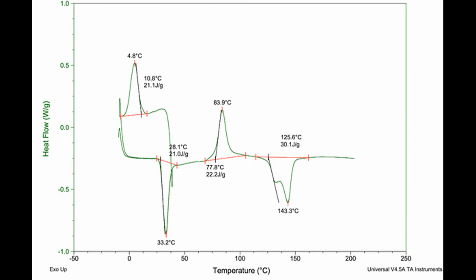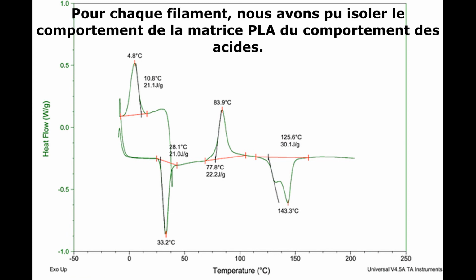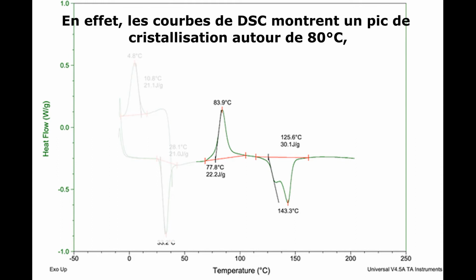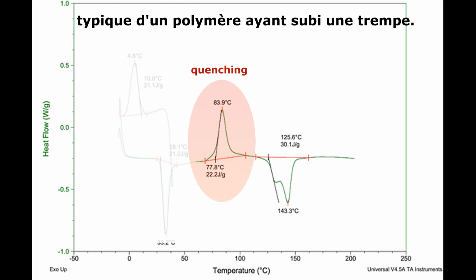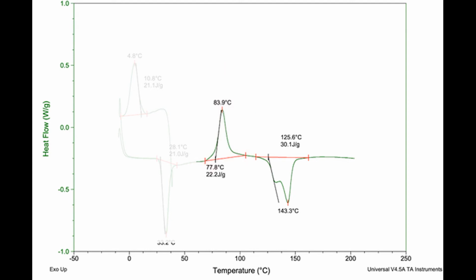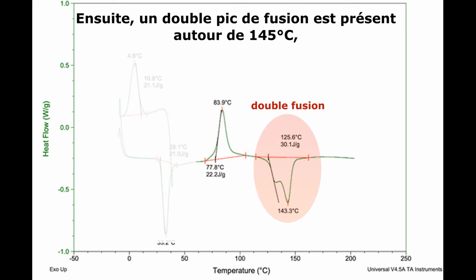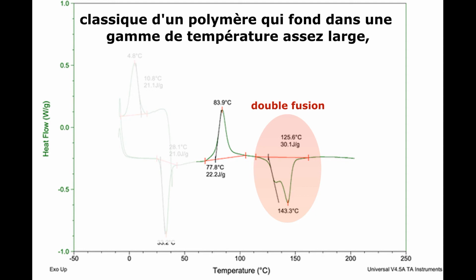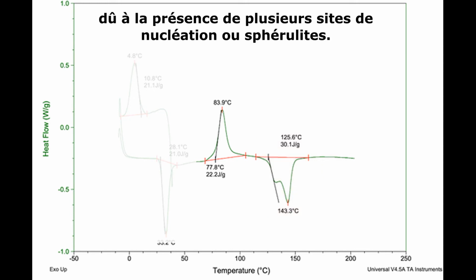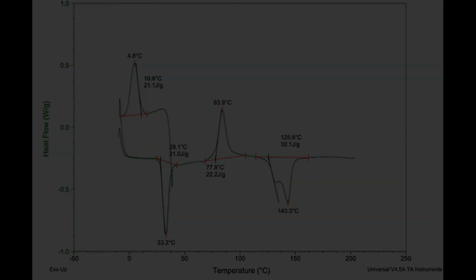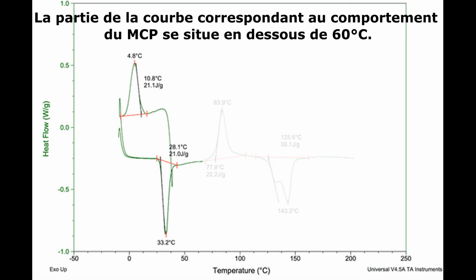Results show the following. For every filament, we could isolate the behavior of the PLA matrix from the behavior of the PCM. Indeed, the DSC curves show a crystallization peak around 80 degrees, typical of a polymer that has undergone quenching. Then, a double fusion peak is present around 145 degrees, classic of a polymer that melts in a quite large temperature range, due to the presence of several nucleation sites or spherulites. The part of the curve corresponding to the PCM behavior is situated under 60 degrees.